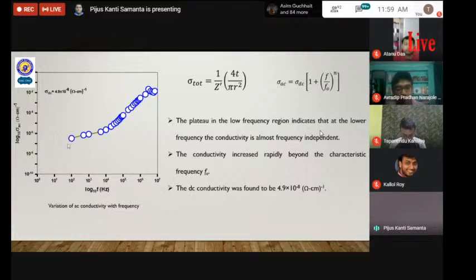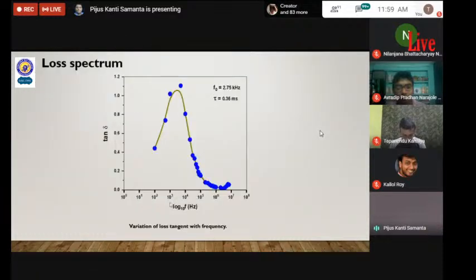A plateau is observed in this low frequency region. It indicates that in the low frequency, the conductivity is almost frequency independent. But as the frequency increases around 10 to the power 4 onwards, then the conductivity goes on increasing. And beyond a certain characteristic frequency, again, it shows a saturated or lower behavior. And the DC conductivity can be calculated from these intercepts, and it was calculated to be 4.9 times 10 to the power minus 8 ohm centimeter inverse. To study the relaxation phenomena, we show here the loss tangent spectrum as a function of frequency,